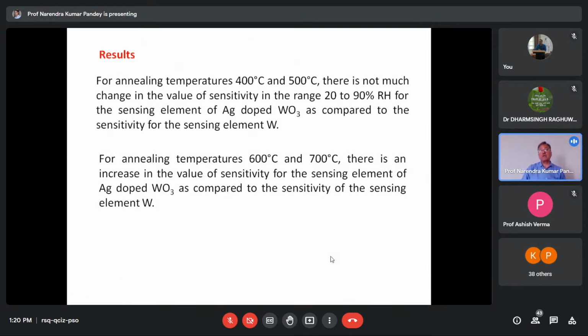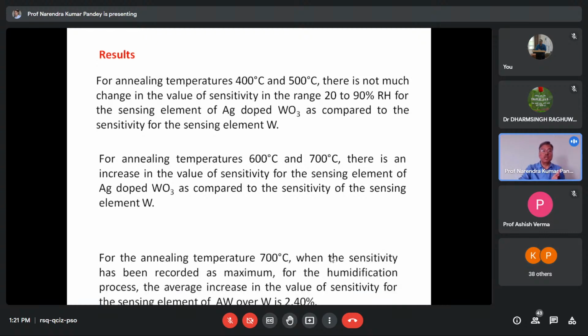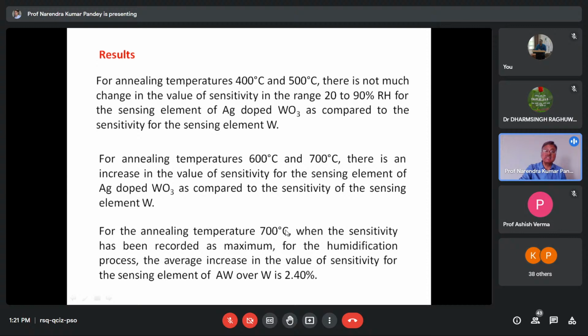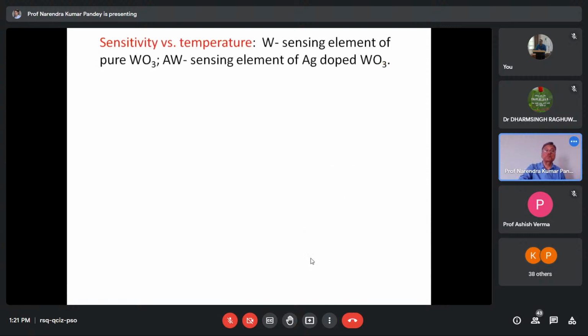For annealing temperatures of 400 and 500 degrees centigrade, there is not much change in the value of sensitivity in the range 20 to 90% RH for the Ag doped WO3 sensing element as compared to pure WO3. But if the annealing temperature is 600 to 700, then there is a significant change in the sensitivity when Ag is loaded. And the sensitivity has increased for 700 degrees centigrade by 2.4% from WO3 to Ag doped WO3. You can see a graph between sensitivity versus temperature.